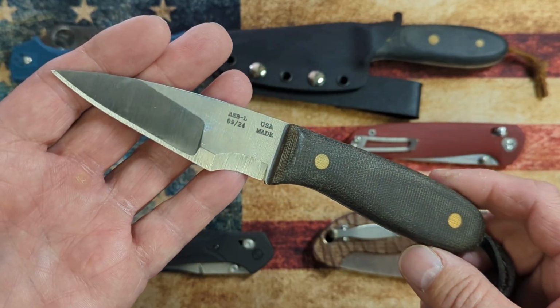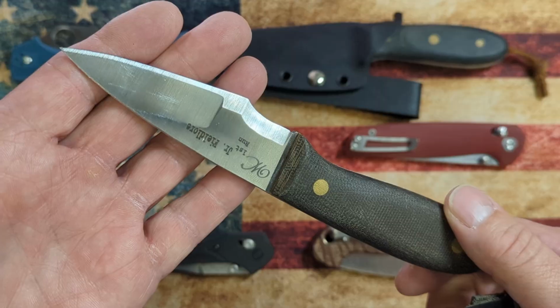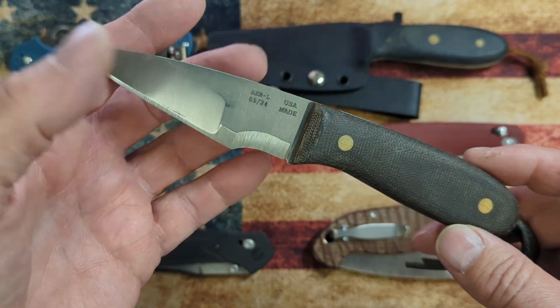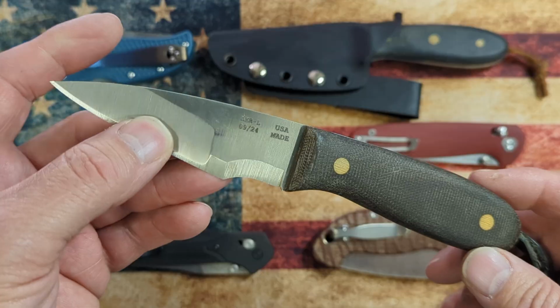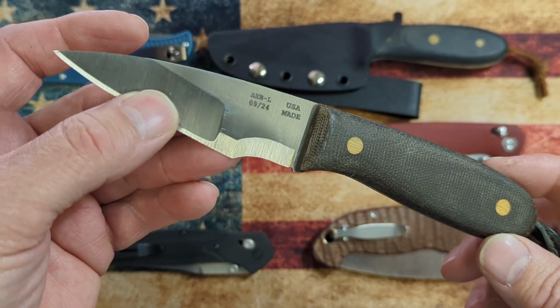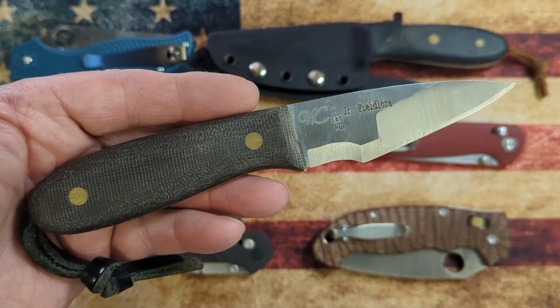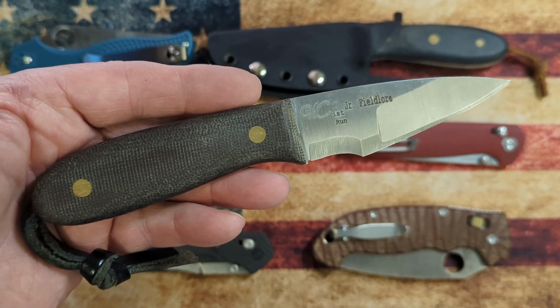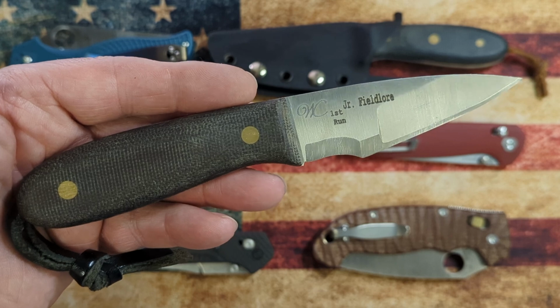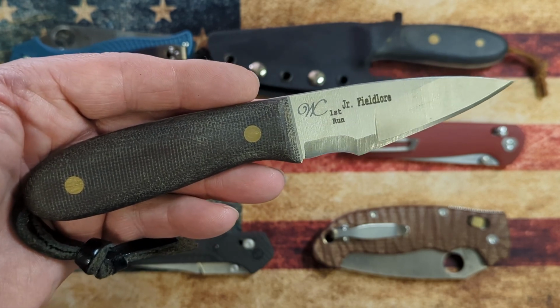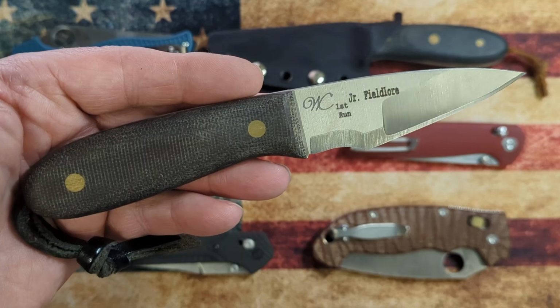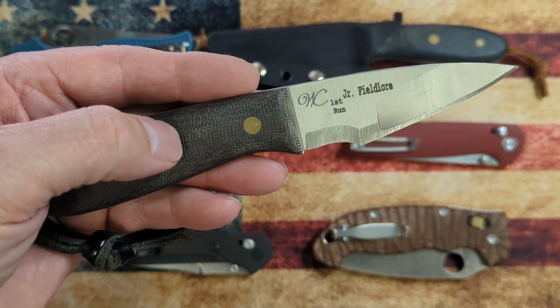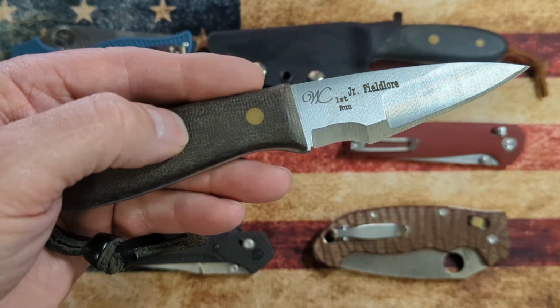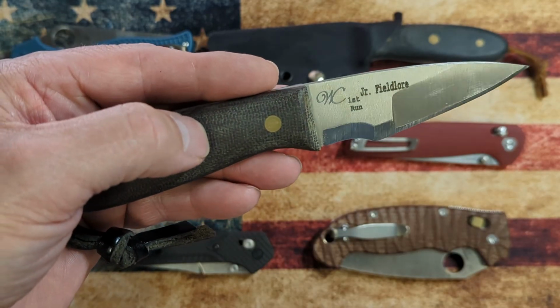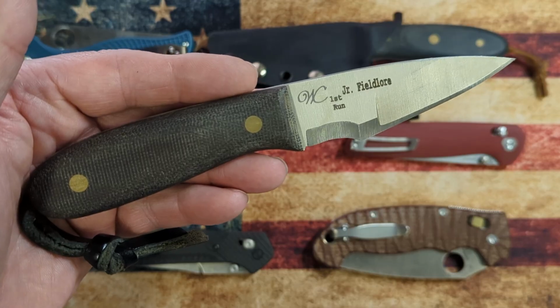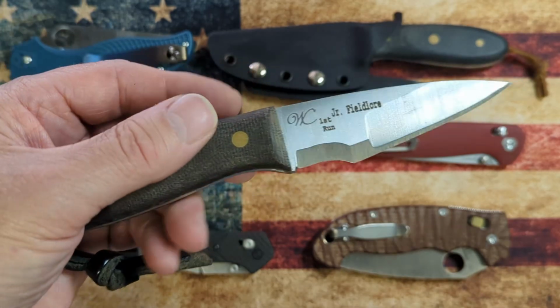Now the downside of it is the wear resistance is stated as a 3, but if you look at steels like 1095, they're only a 1.5. So this starts out as quite a bit better than that, and I believe 420HC only is 1.5 or 2 on edge retention. When AEBL is run around 63 Rockwell, it holds an incredible edge. It jumps up into the next class of steels. So not only do you have a steel that is really tough and it'll take abuse out in the woods, it also has very good edge retention and it can be sharpened at a very low edge angle. All these attributes combined and the fact that it is stainless makes this an ideal steel for a woods knife.